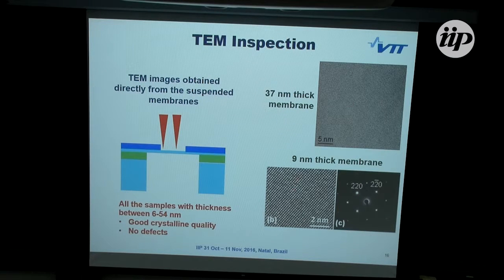So no defects, and then there's a 9 nanometer thick membrane, so no defects, and the diffraction pattern gives very nice spots. Have to say that if one keeps the electron beam on one spot for long enough, and the membrane thickness is very small, then one starts to amorphize this, but that's eventually. So no defects, good crystalline quality, and well below 10 nanometer thick membranes.